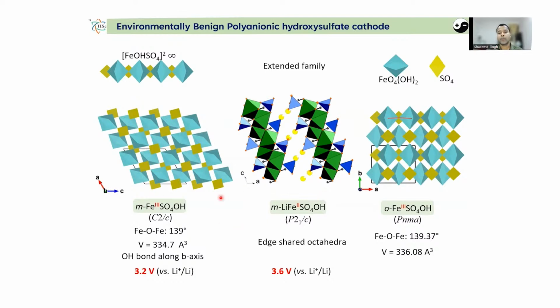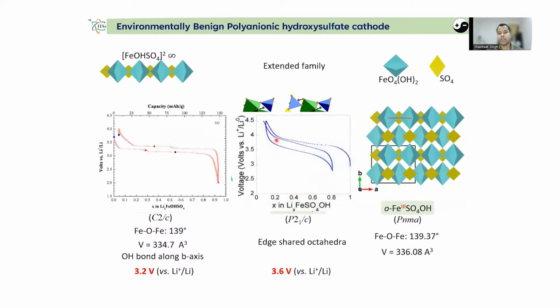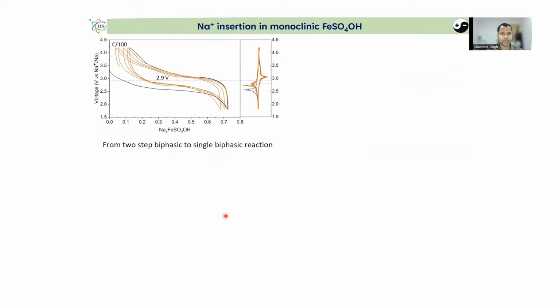Later on, its polymorph, monoclinic LiFeSO4OH, showed a solid solution reaction. So the mechanism changed from a sharp biphasic reaction to a solid solution reaction mechanism. Also, in the literature we found that there is an orthorhombic FeSO4OH which remains unexplored. So we wanted to see the effect of the different structure on the reaction mechanism. Further, we wanted to repurpose this monoclinic phase as a cathode material for sodium-ion batteries.